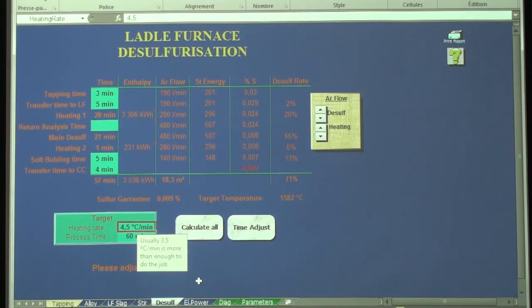When you talk about heating rate, how can you check a heating rate whenever you allow yourself to put some stuff in the ladle? How much? Is it flux? Is it the oxidization? Is it manganese? Is it molybdenum? Whenever you talk about heating rate, it is all the time without any addition. So when we check, we compensate the alloys -1 degrees and so on? No, forget it. It's stupid. In your case, the heating rate is only 4.5 per minute, without alloys. When you talk about heating rate, never allow the customer to put alloys. Otherwise, you have to fight for hours about what is the influence of the lime, what is the influence of...